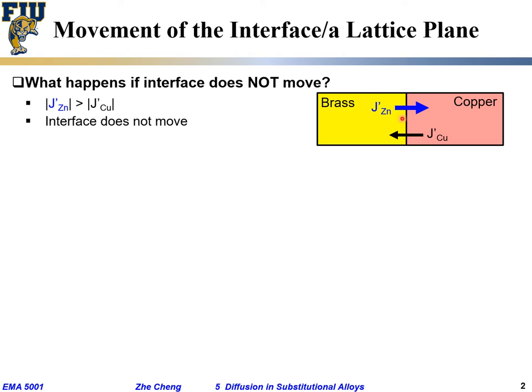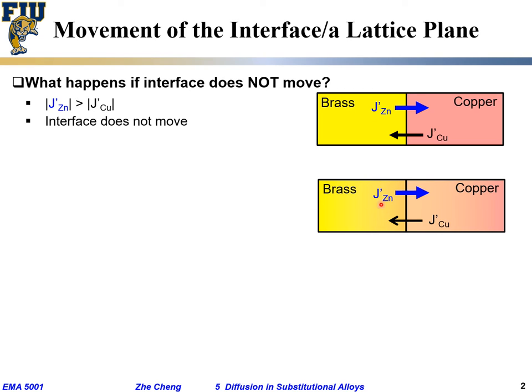Which means the amount of zinc atoms that flow from the left to the right is greater than the amount of copper that flows the other way. What if the interface does not move? What would happen? If this interface between these two parts does not move, but I have more zinc going out than the copper coming back, what would happen to the brass side? I would have, as I change the color, if the interface doesn't move, so-called excess vacancy.